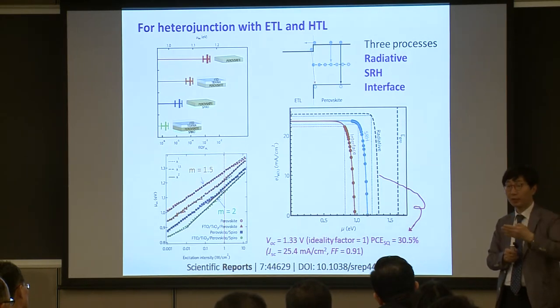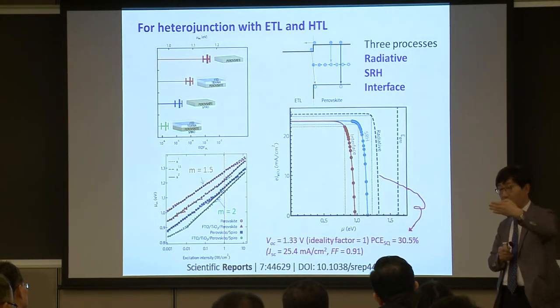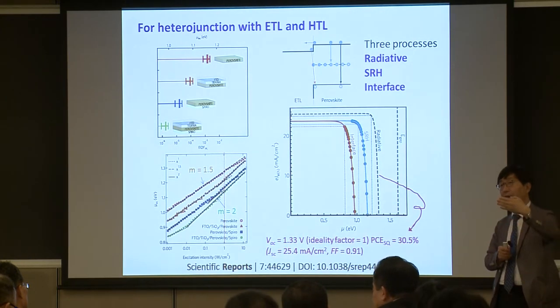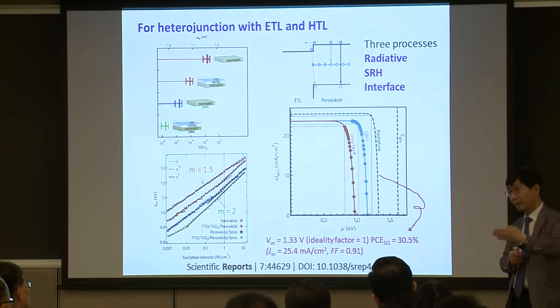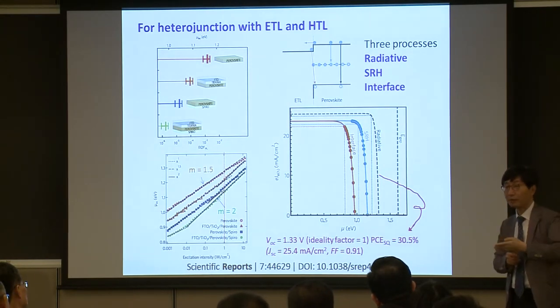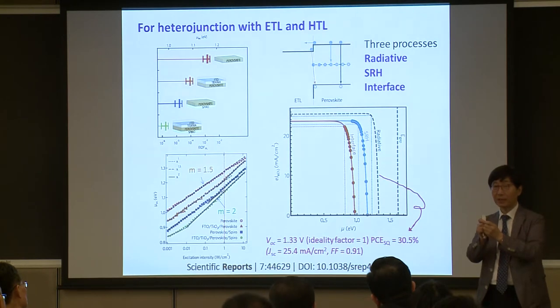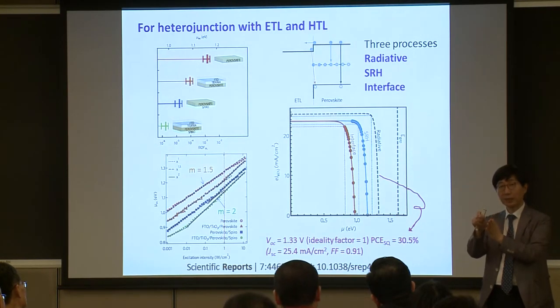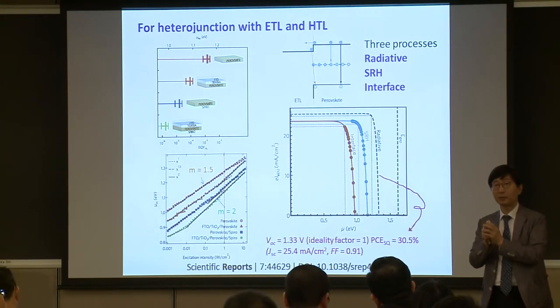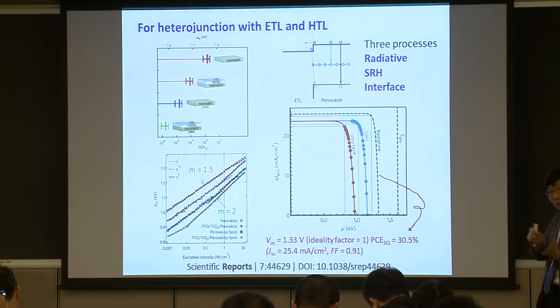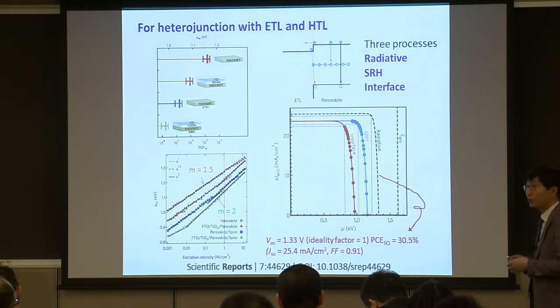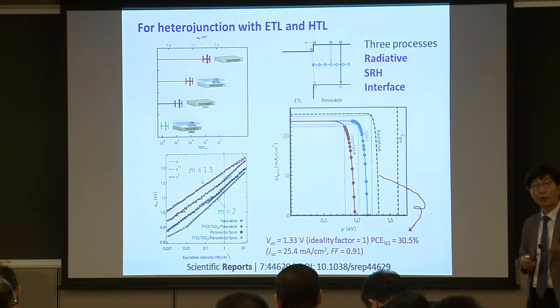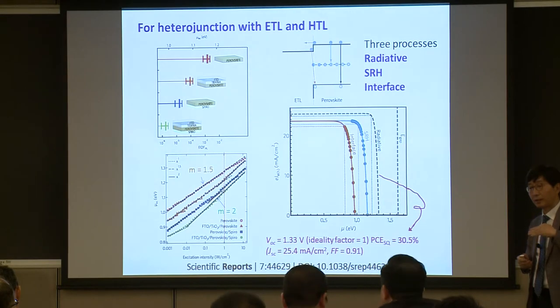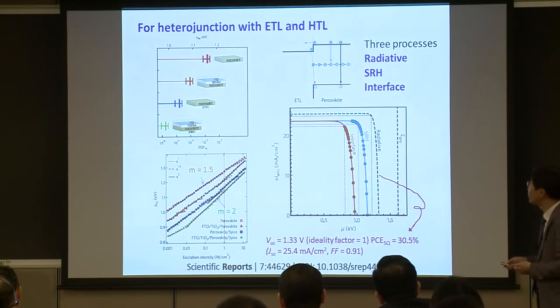Recently, I found that by TEM measurement, we prepared the whole device and then did the J-V measurement, okay? And then a very thin cross section was prepared to measure TEM. Then we found some crack between this spiro compound and the perovskite, meaning that it's a poor interaction between the spiro and the perovskite. Also, the titanium oxide. So the surface management of the ETL and HTL is very important.